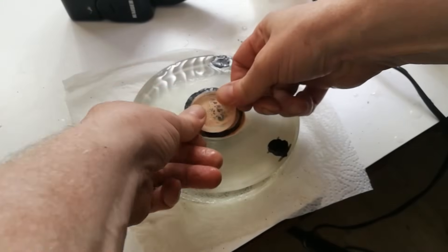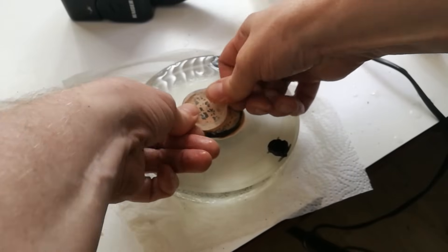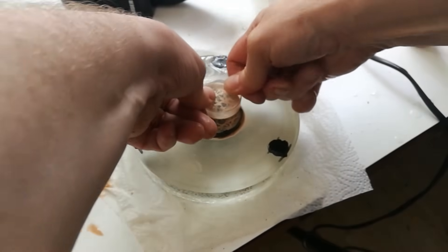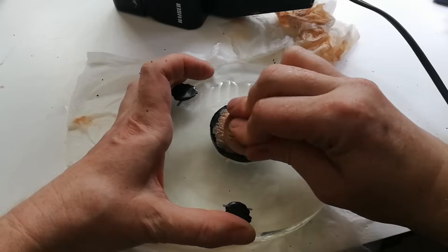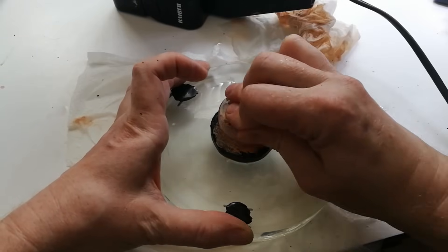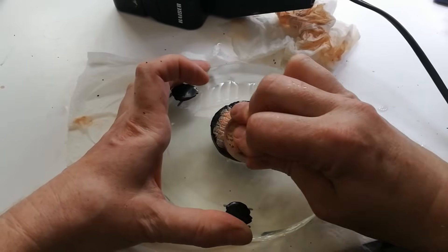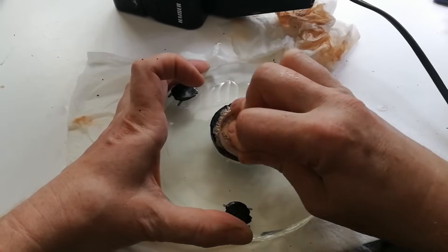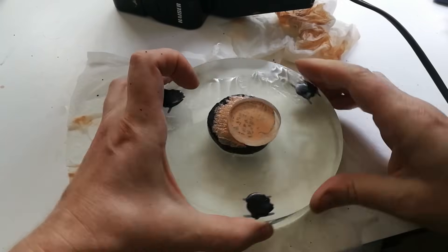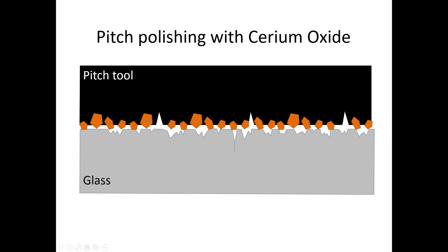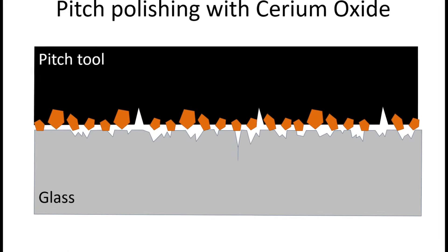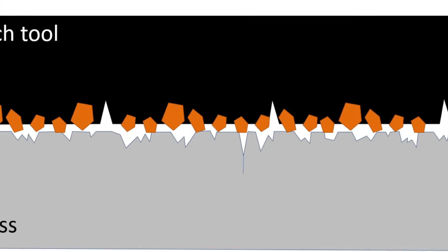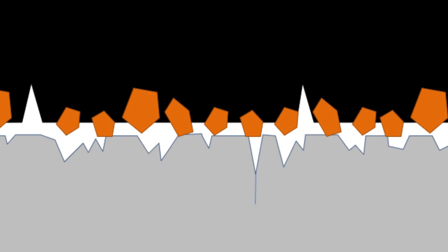When satisfied with the surface shape and with the blank and the polishing tool at a very well-defined temperature, we can start the actual polishing process. So a few drops of cerium oxide suspension are applied to the tool. The cerium oxide particles are generally a few microns in size, but they are much softer than grinding particles and less sharp, and they can embed into the pitch. So this is the reason that we can bring down the surface roughness of the glass from let's say a few microns down to a few nanometers.